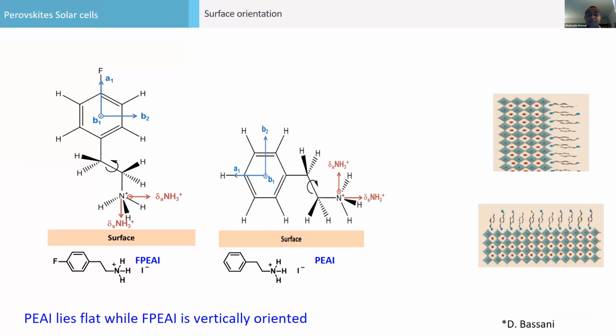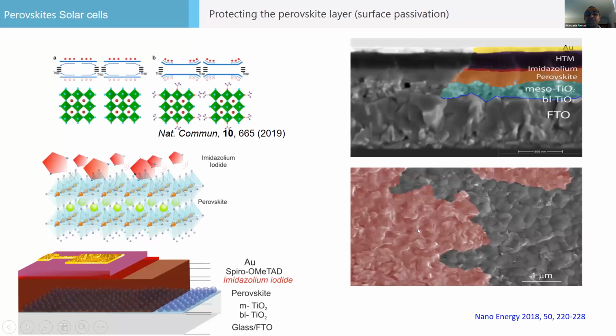And we collaborated with some people who were very good in different spectroscopic techniques. And we see both these molecules have a different orientation on the surface. We calculated from the stretching band of NH3, and this gives you a different value. So in case of PEAI, it lies flat on the perovskite surface, while the FPEAI is perpendicular to the surface. And that's why this different orientation of the molecule sitting on the perovskite gives you different electro-optical properties. Let's go down later. I think I'm running out of time.